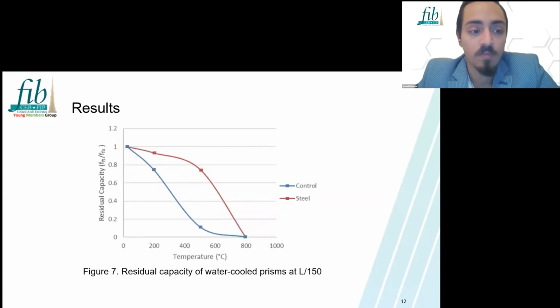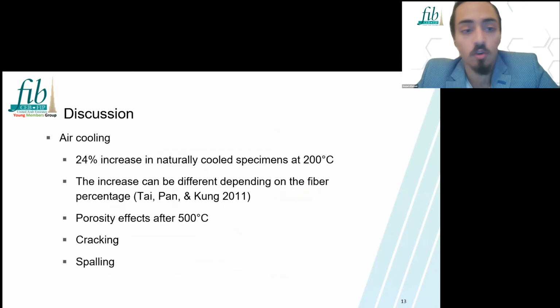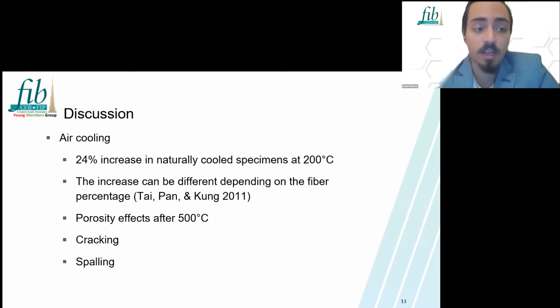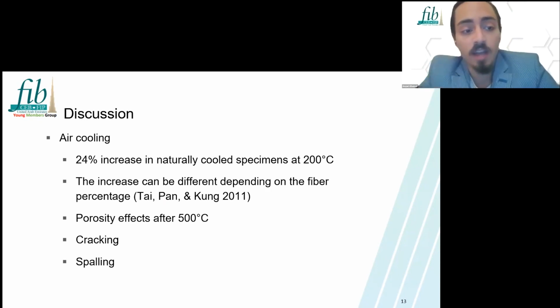For water cooling, on the other hand, the results are slightly different. From figure 7 on the screen, you can see that there was no strength increase at all. Both of them started to decrease directly. However, the steel fiber lightweight concrete mix could always sustain more of its strength than the control mix. Now onto the discussion. We found a study in the literature that has a similar increase in strength, but they used reactive powder concrete.